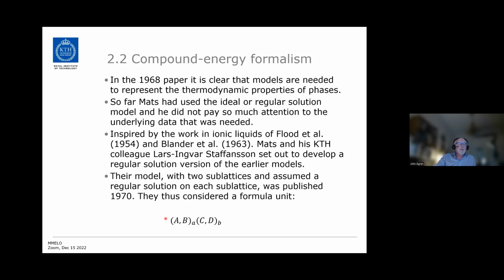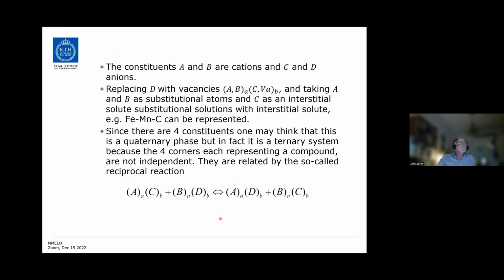So they consider a formula unit like this with A and B on the first sublattice, C and D on the second. And A and B would then, for example, be cations, and C and D anions. Now, if you replace D with vacancies, you look at this formula unit and take A and B as substitutional, and C as interstitial solute. Then you can use this as a model for an interstitial solution of this type.